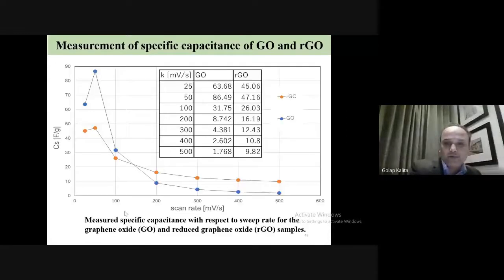Then we can calculate the specific capacitance from the previous equations, and we can see that the specific capacitance is more than 80 farad per gram for the graphene oxide sample. Of course, we need to enhance the capacitance much more, but we show that this type of graphene oxide and solution-based synthesis materials can have very good capacitance, and we can develop some supercapacitors based on this material.